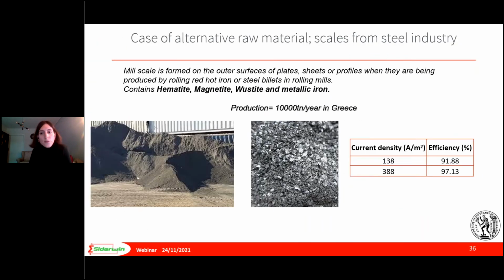Another alternative raw material that is very attractive for the Siderwin process is mill scale. Mill scale is produced by rolling red-hot iron or steel billets in rolling mills. It contains high percentages of iron oxide, with hematite being the predominant, and also metallic iron. A few experiments have shown that this material is promising for the Siderwin process, achieving high current efficiencies such as 97%.